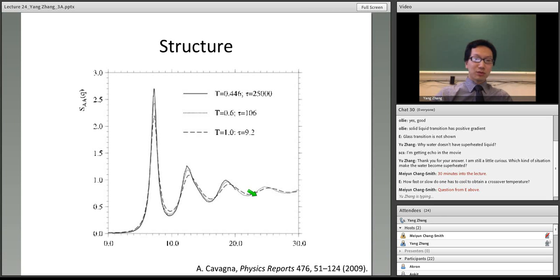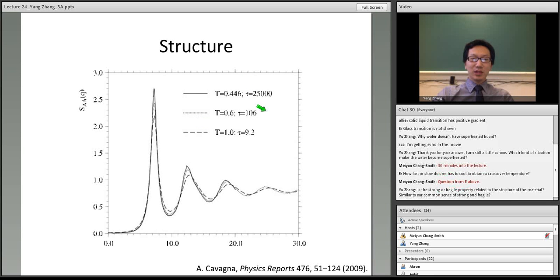But it's natural to think about the structure. So in this slide, I show you the structure factor of a binary Lennard-Jones system at 3 different temperatures. When I change the temperature, you see the structure factor of the material doesn't really change much. There are some small changes, very subtle. But the dynamics, like the relaxation time, change from 9.2 to 25,000. It's many orders of magnitude.